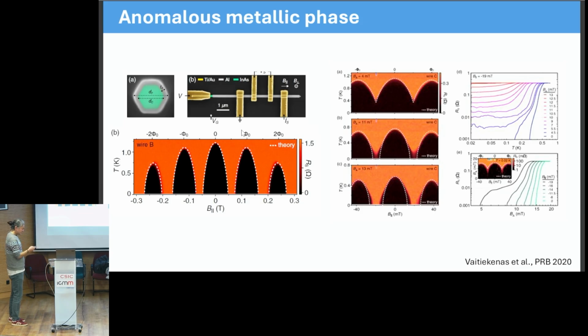This is an interesting work, and one of the works that actually motivated us to study a bit of this physics, from the Copenhagen group, where they studied the superconducting properties of this hybrid material. The nanowire, in this case, is fully covered by the superconducting shell, which leads to interesting physics, namely when one applies a magnetic flux perpendicular to this wire cross-section, one sees a modulation of the critical temperature of the superconductor due to the quantization of fluxoid. So this is known as the Little-Parks effect.